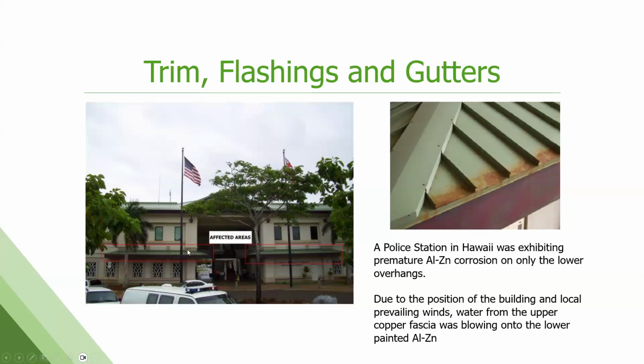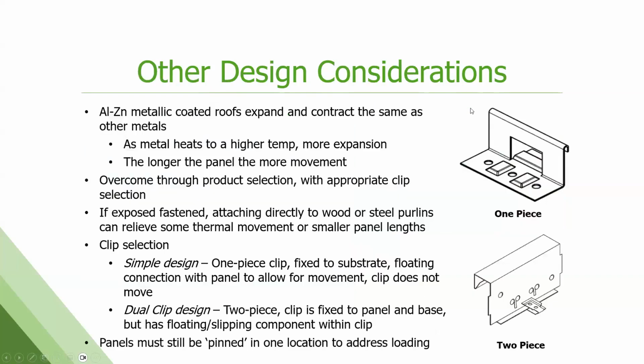No. A few years in, they had accelerated corrosion occurring along the edge of the bottom roof line only. We went and inspected it. What we found out was that due to prevailing winds and rain patterns, we were getting rain droplets falling off of the top copper fascia onto these panels and running down to the edge and sitting, causing premature corrosion.